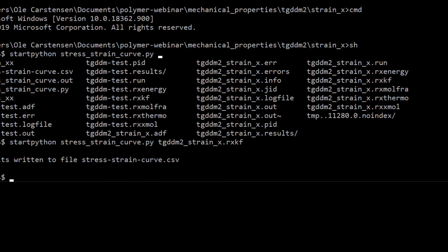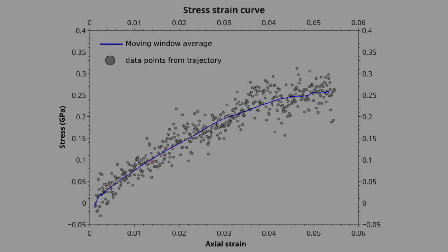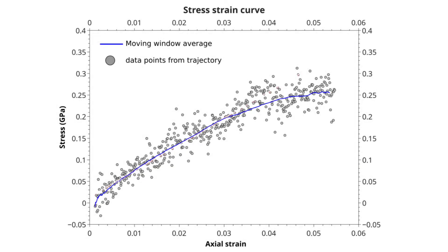The stress-strain curve is written to a file called stress_strain_curve.csv. In this results file you will find the x, y, and z strain in the first three columns, and the x, y, and z stress in the last three columns. It can be plotted with any plotting software, for example GNUplot, Origin, or QTIplot. To calculate the mechanical properties from the raw data, we follow the approach outlined in the Odegard paper. First, we smooth the curve by calculating a moving window average — in this case, 200 frames were used for the averaging.